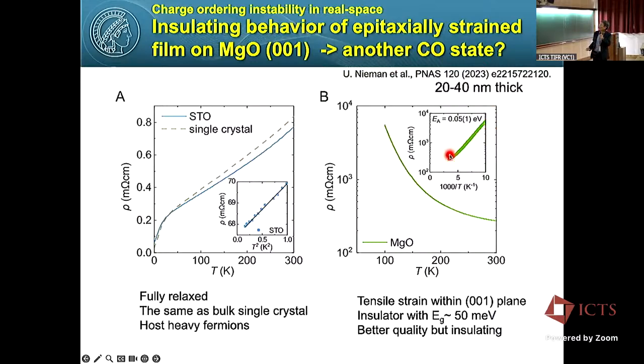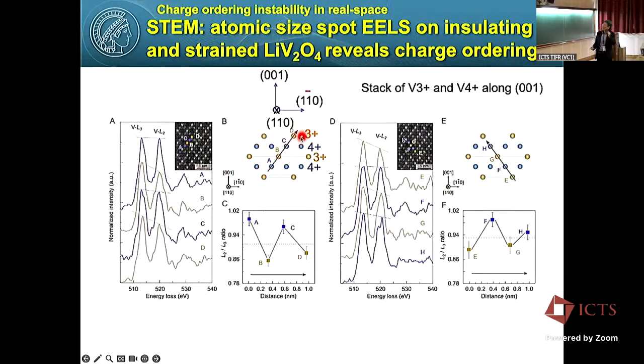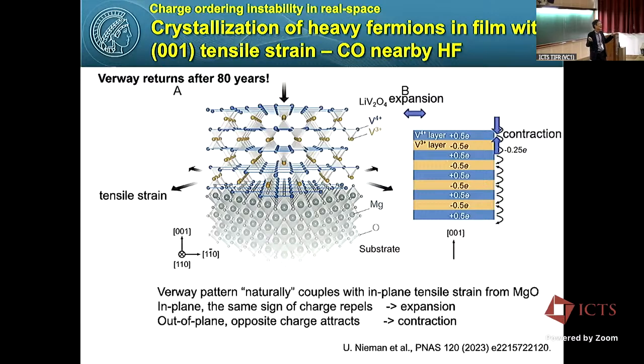But going to the strained film, although the film quality is better than this one, somehow we do see insulating behavior with an activation energy of 50 millielectron volts. It looks like an insulator, perhaps a charge ordered insulator. And we tried to look for the signature of charge ordering using a STEM microscope with atomic size EELS. So here is the lattice, and we can check the valence of vanadium from atom to atom using this spectrum. And we found that along this line, the valence is 4+, 3+, 4+, 3+, and along this line also 4+, 3+, 4+, 3+ experimentally. And this without any doubt gives a charge ordering stack of vanadium 3+ and 4+ along the 001 direction, perpendicular to the film plane.